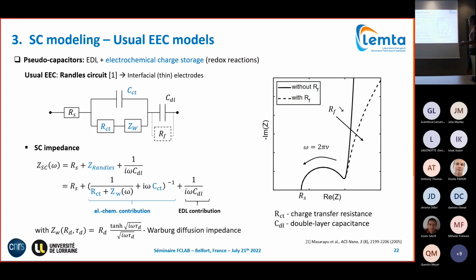That's all we need at the moment. It depends on the characteristic diffusion time and the diffusion resistance. Okay, these are our parameters. So this is the electrochemical charge storage contribution. Again, you find the series resistance. And as I said, even for pseudocapacitors you always have a contribution of pure capacitive charge storage that can be modeled by a double layer capacitance. And if you want, again, you can take into account leakage by connecting a leakage resistance parallel to the double layer capacitance. Here on the right side, you see the typical Nyquist plot of these kinds of supercapacitors.